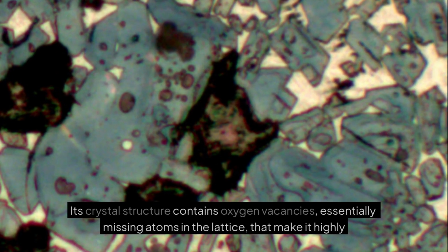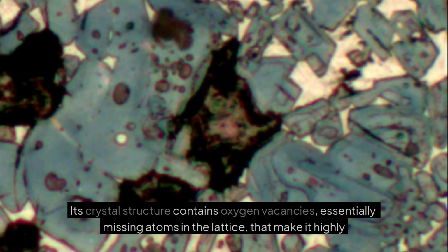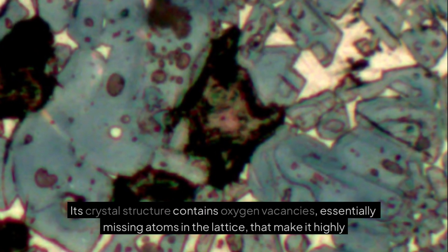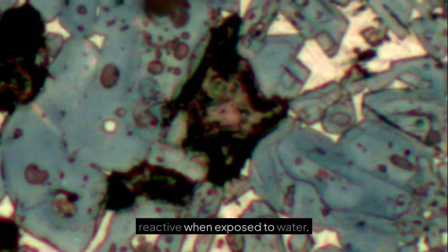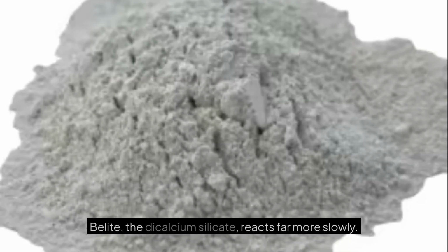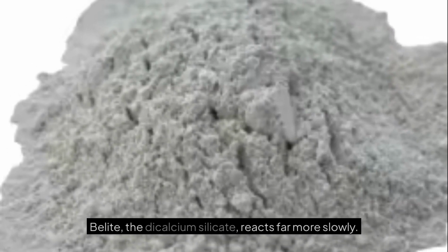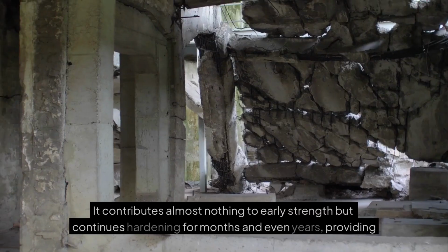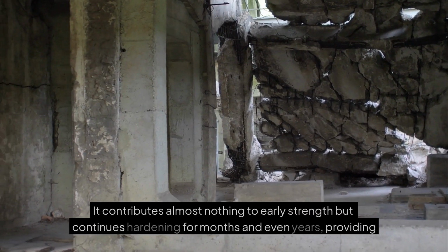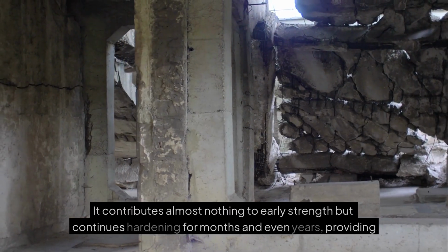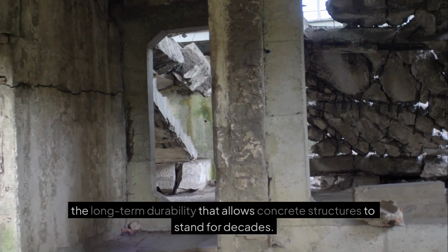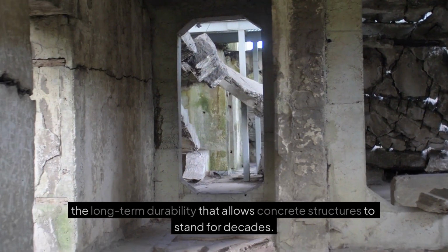Its crystal structure contains oxygen vacancies, essentially missing atoms in the lattice, that make it highly reactive when exposed to water. Belite, the dicalcium silicate, reacts far more slowly. It contributes almost nothing to early strength but continues hardening for months and even years, providing the long-term durability that allows concrete structures to stand for decades.